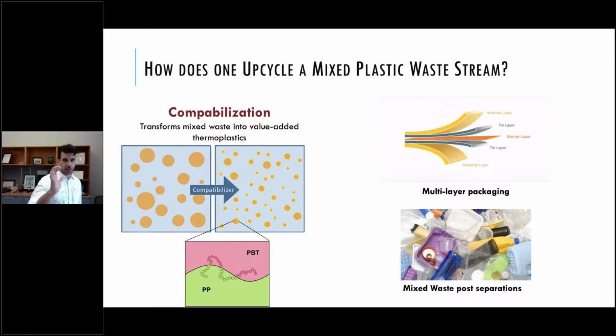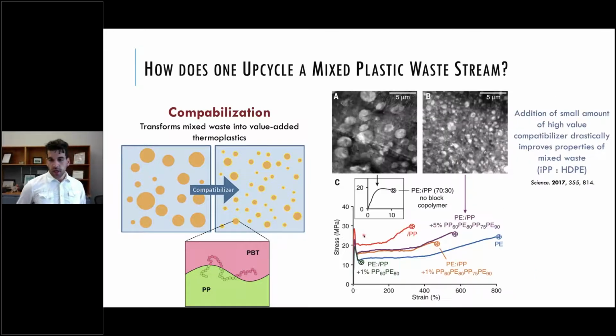So post-separation, often in a material recovery facility, you have, let's say, a sink fraction that is composed of a lot of different plastics, or you may even have a cut of one of the float fractions that contains, let's say, polyethylene and polypropylene together, right? If you can compatibilize those materials selectively, again, you can get a higher value material out. So here's an example, this science paper that was published a few years ago. In this case, isotactic polypropylene, high density polyethylene. These are common materials that after separations are found in a mixed float fraction.